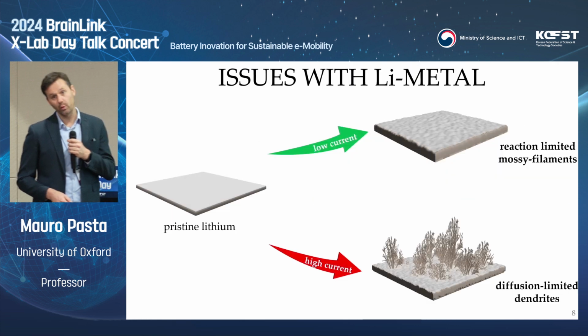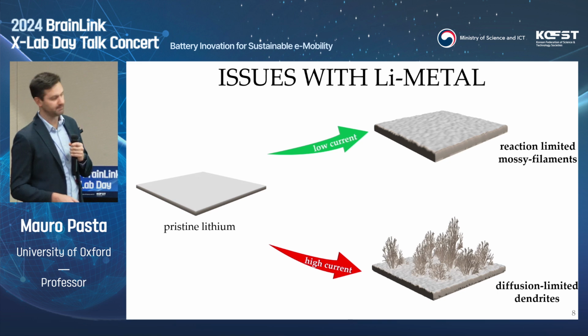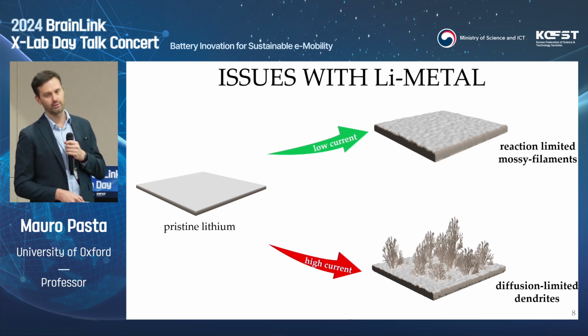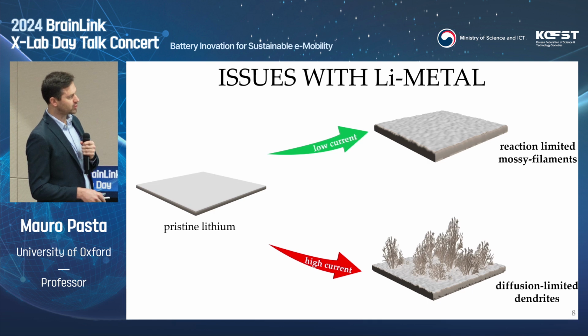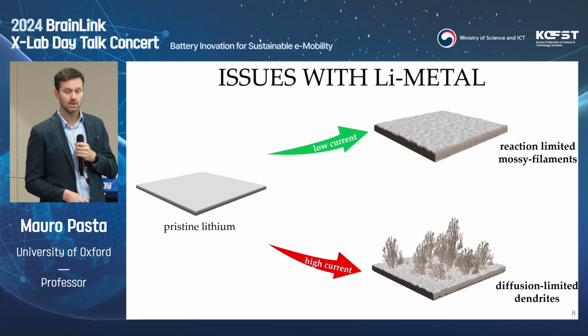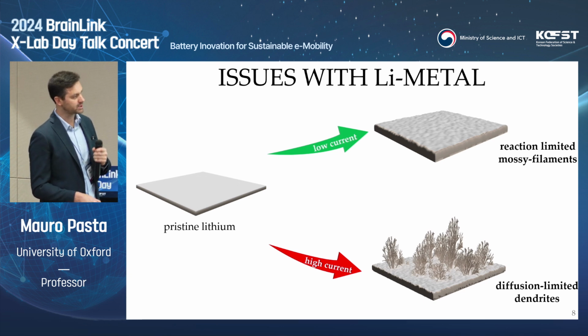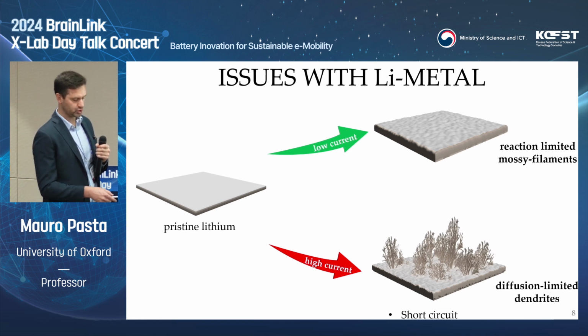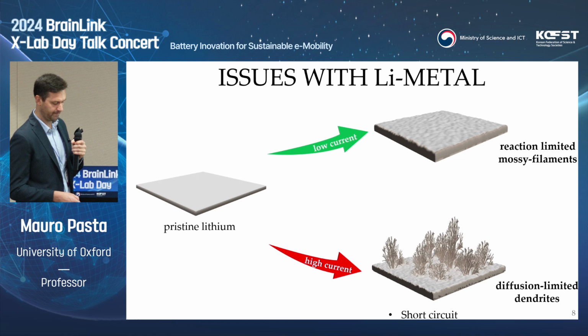So now the question is, why aren't we doing this in a liquid electrolyte? Well, the problem is lithium doesn't like to plate uniformly. So if you try to plate at high current density, you enter this diffusion limited regime where dendrites are forming. Dendrites are filaments of lithium that are mechanically strong enough to pierce through your separator and short circuit your battery. And that's a recipe for disaster in a lithium-ion battery, as you have a flammable organic electrolyte. If the temperature increases, you also have problems of oxygen release on the cathode side that often leads to not only dendrites and short circuit, but also to catastrophic failure.